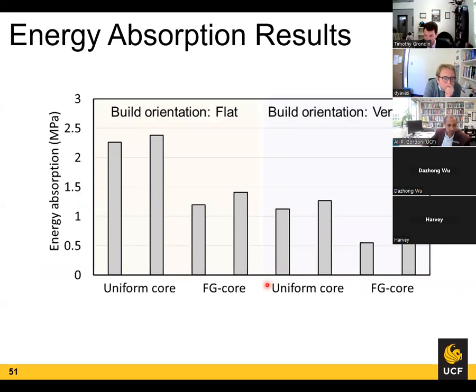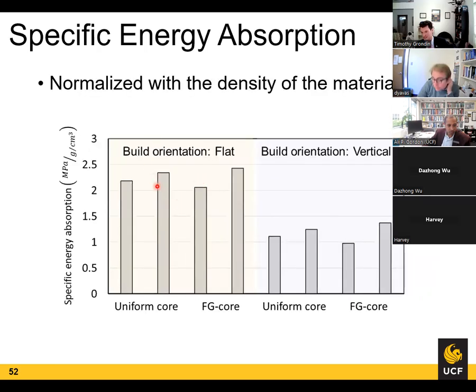Now, categorizing this in specific energy absorption, which has been normalized for the density, you can see that the normal energy absorption in the uniform core is higher, but now we're going to take the density out of that, normalize it again, and we show that overall the flat build orientation is almost the same, with the functionally graded performing slightly higher in both instances on the flat orientation, and the same functionally graded barely higher in the vertical print orientation. So again, a design trade-off, and we attribute this to the progressive failure versus the catastrophic failure, and the build orientation is definitely most likely the driver between the ductile versus the brittle behavior.